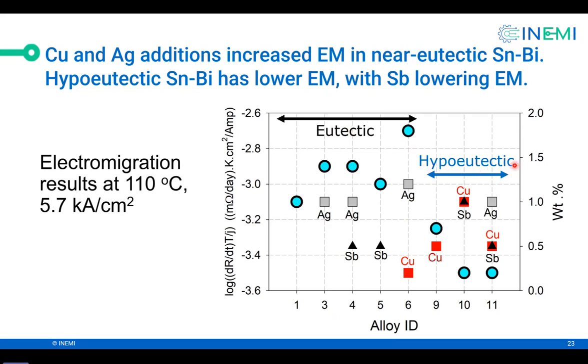Now, hypoeutectic, which contains a lot less bismuth, in general, the rate of electromigration is less. But copper tends to increase the rate of electromigration in hypoeutectic, and antimony decreases it. Here's antimony, here's antimony. Because of antimony, the rate of electromigration has come down. So you can say copper increases the rate of electromigration and antimony decreases it. So these are our findings, but let me show you how we got to them. And there are other interesting observations we made along the way.